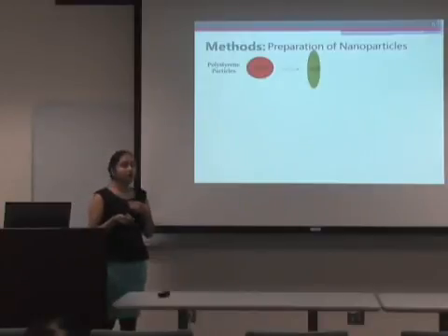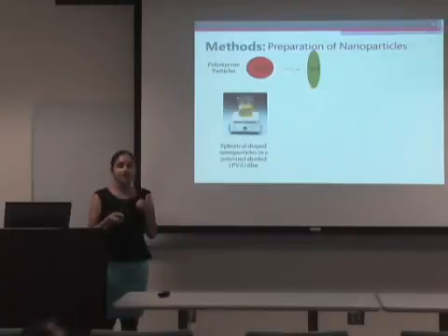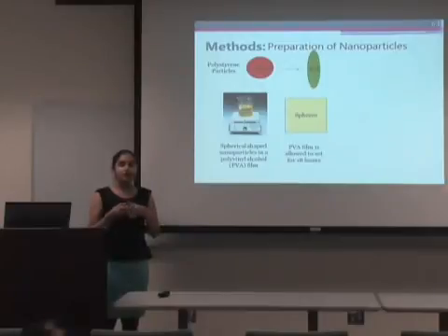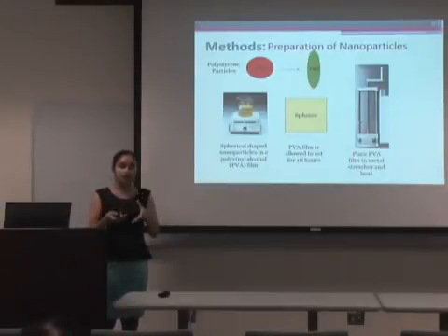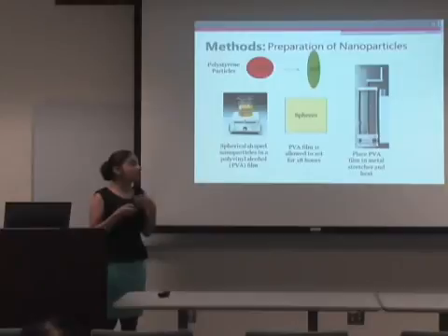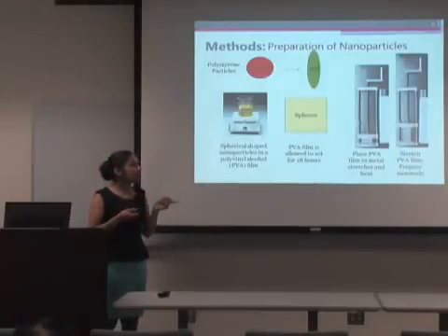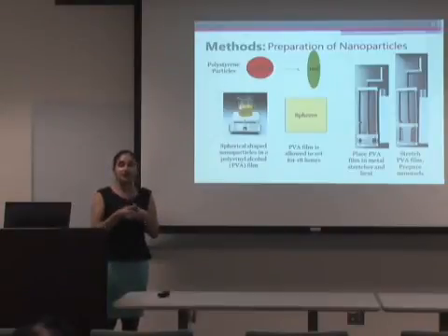The first part of my project was to take the nanospheres that are delivered to our lab and turn them into nanorods. The way we do this is that we first coat the nanospheres in a polyvinyl alcohol film, and we let the film dry overnight. Once we have this very thin film, we place it in a metal stretcher, as you see here, and then we heat the entire device in oil. As we're putting it in oil, we stretch the nanoparticle film, and as we stretch the film, we're turning these spheres into rods. Then we recover both sets of particles.